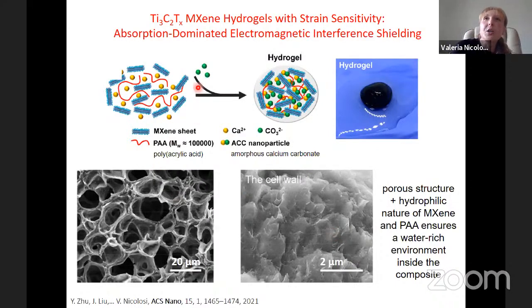For example, we are using MXene inks to make hydrogels with polyacrylic acid and amorphous calcium carbonate. We link them and we form some lovely hydrogels, which are nicely porous. They are hydrophilic, which is very good for certain applications. It's always good to have a water-rich environment, especially if you want to use this for EMI shielding, electromagnetic interference shielding. And this is what we thought was an application for us to seek for these hydrogels.